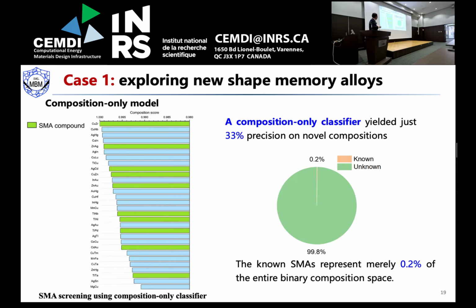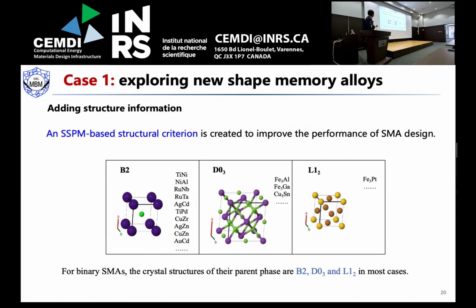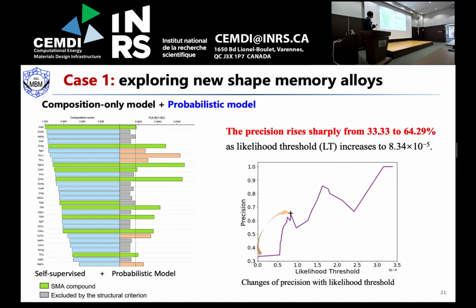The reason is that the data set for the well-known shape memory alloys is only 0.2%. So if you only use the data-driven method, the accuracy is not so good. Then we have to add the structure information. For example, for shape memory alloys, we know they usually have the B2 structure, D03 structure, or L1-2 structure. So if you add this structure information to this model through the probabilistic model, then we can predict.